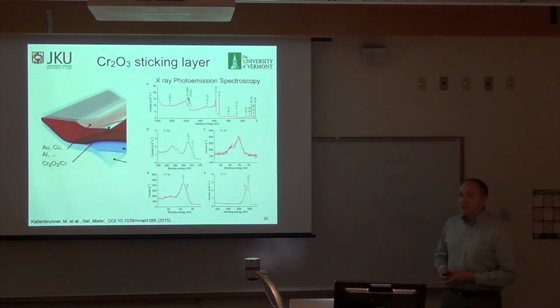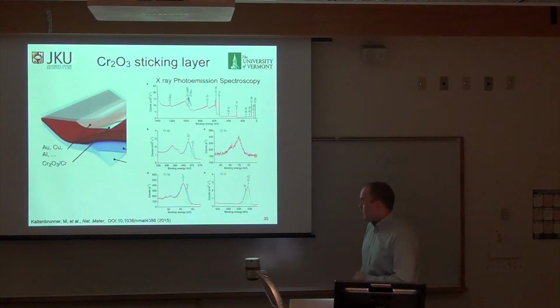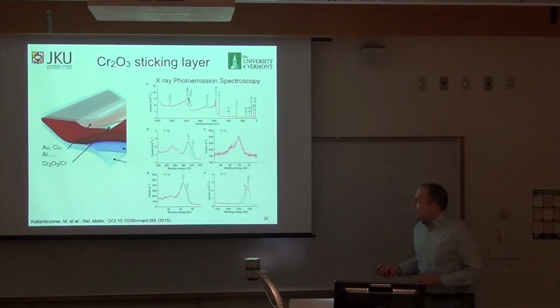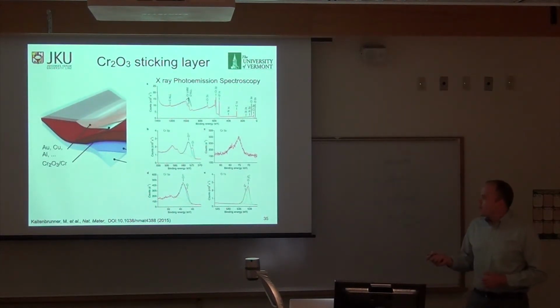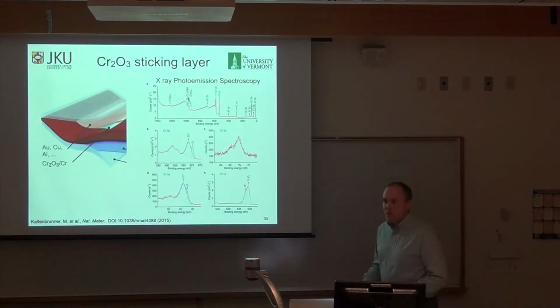This is an extension of the photoelectric effect we did yesterday, and we can really use it. We put this chromium oxide layer in, and the devices become much more stable. I'll quantify that later. But more importantly, it allows us to use gold or cheaper metals like copper or aluminum. It doesn't matter, we can put whatever metal we want on the back, and the devices are equally stable and equally efficient.